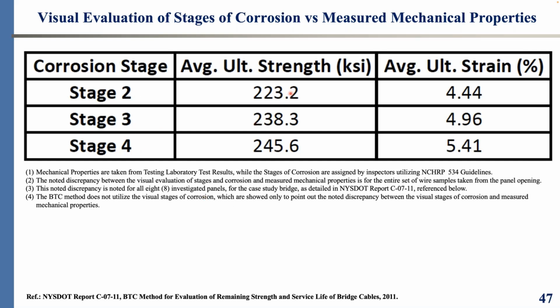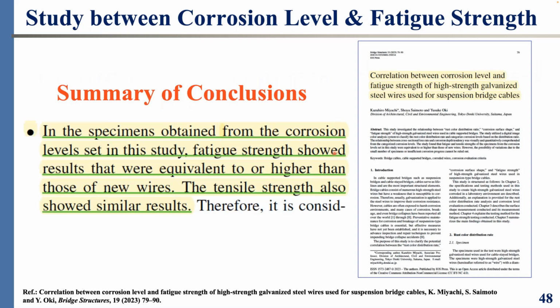Well, this kind of discrepancy is not happening for just a couple of wires. It's for the entire set of samples. I show here one panel, but in that report that I'm referencing down there, you can see the entire 8 panels where all of them have this kind of discrepancy to one degree or another. So moving along, we see that in just about all the cable investigations we have worked with, there is no correlation between the visual measure of corrosion and the actual measured properties, neither in tensile strength or fatigue life.